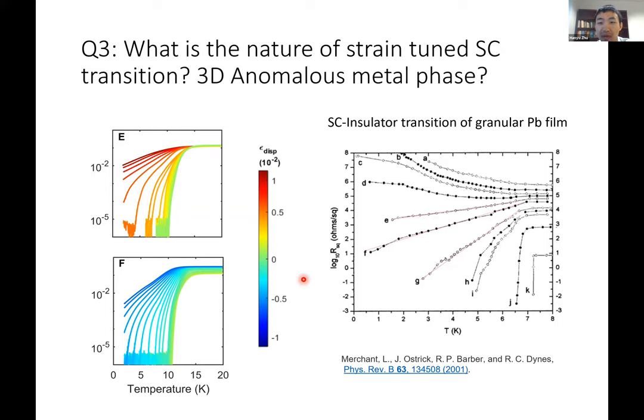Is there a way to control that parameter? Yeah. So that's how the elasticity does, right? You're right that if you fix the system, there could still be structural fluctuation. But let's say if you strain a crystal, you're basically suppressing structural fluctuation by forcing the structure to be strained in a certain way. And then while you're doing this, you can ask the question, does the electronic system still become more and more anisotropic as you're lowering the temperature? And if it does, then that means that the electronic system really has an instability to go towards a phase transition.